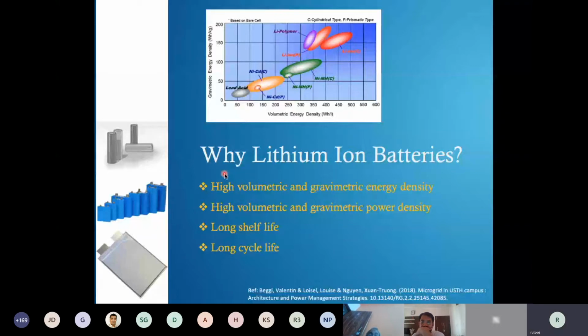Then among batteries, why lithium-ion batteries? Probably most of you know, lithium-ion batteries have the highest energy density among all the available commercial chemistries. For example, lead has about 50 to 100 watt hours per liter, whereas lithium-ion batteries have around 400 to 600 watt hours per liter. Again, this data is a little old. Now the volumetric energy density at the cell level has gone up to 600 or more than 600 watt hours per liter in some cases, depending upon the geometry.